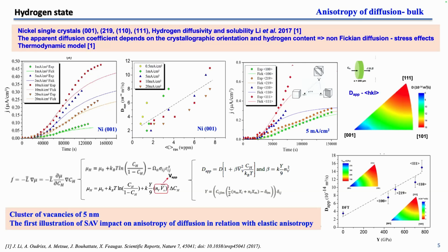The second result is the fact that the flux depends on the orientation when we charge the surface, and we have anisotropic results. This result is mapped with a specific map, in this small figure, and we represent the tensor of the diffusivity in this map. We have shown that we have a high diffusivity near this orientation and a low diffusivity in this orientation. This inverse pole figure is quite similar to that of Y. This parameter describes the anisotropy of elasticity in this material, and we show that we have a nice correlation.